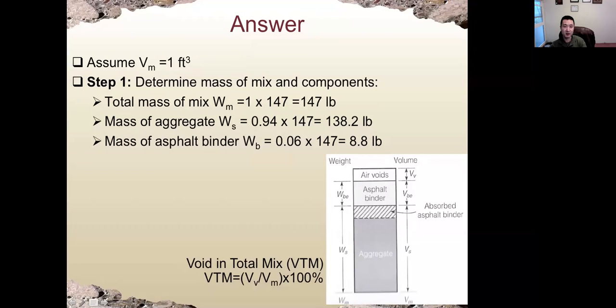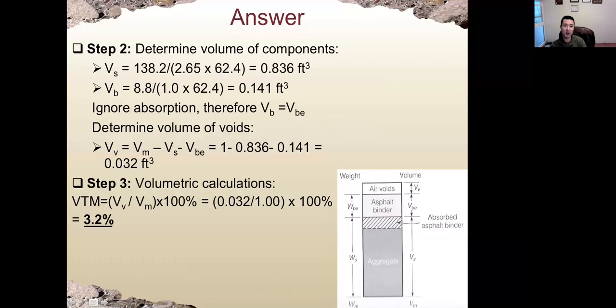And then based on the weight, the mass, we can calculate the volume. For aggregate, the total weight is divided by 2.65 times 62.4. This is the specific gravity of the aggregate, this is the density of water, so this is the density of aggregate. So the mass divided by density is the volume occupied by aggregate. Similarly, we can calculate the volume occupied by binder. So it's 0.141 cubic foot. The question tells us to ignore the absorption, so the effective binder, VBE, will be the same as the volume of binder, 0.141 cubic foot. The remaining volume will be occupied by voids.